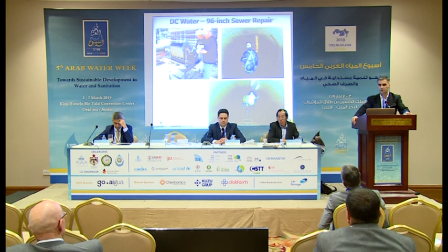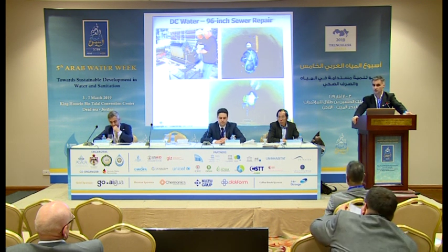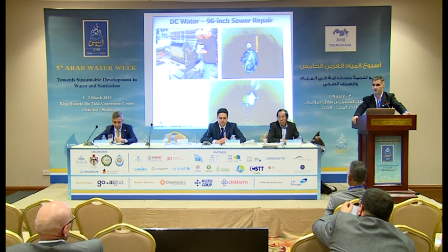A case study from DC Water: it's a 96-inch sewer pipe. Ironically, the host pipe is a glass fiber reinforced pipe — centrifugally cast, not to be confused with our systems — but generally a good pipe. However, they had a localized failure, so we went in and lined it with our FRP system. In the upper left you can see a saturating machine — that's how we saturate fabrics in the field, and it can be taken inside the pipe as needed.